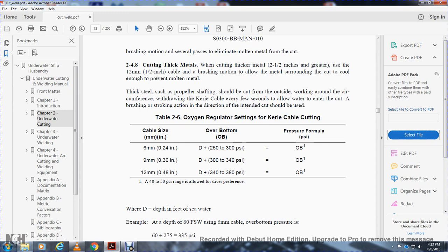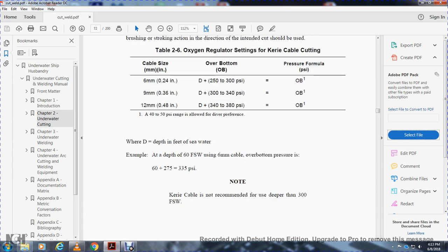Regulator settings for the Kerie Cable. For the 6mm cable, use 250 to 300 psi, depth in feet of sea water, plus 250 psi of oxygen, equals OB1. For the 9mm, 3/8 inch cable, the depth in feet of sea water plus 300 to 340 psi equals OB1. For the 12mm, 1/2 inch cable, the depth in feet of sea water plus 340 to 380 psi equals the OB1 pressure formula.